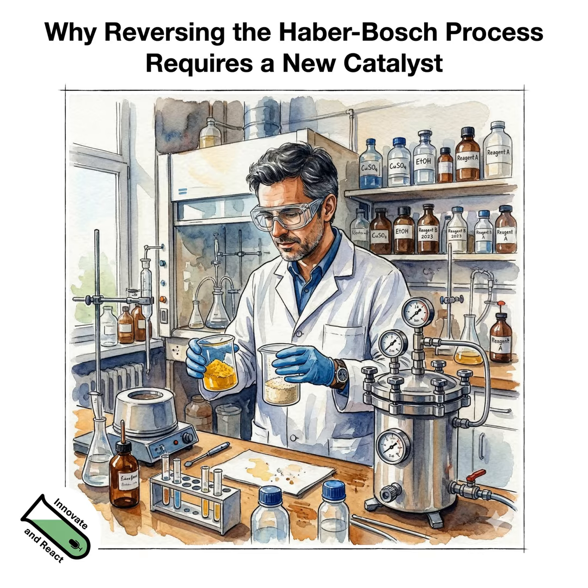Exactly. And we confirmed this recently in a collaboration with another theory group that looked at the kinetic barrier for the nitrogen at the surface to go subsurface, into the bulk, and form a nitride. That was limited to a large extent by the presence of cobalt in the catalyst, which makes the nitrogen coverage at the surface higher. It does not go subsurface, but it can react and form dinitrogen. Because the recombinative desorption of the dinitrogen is in very many cases the rate determining step.